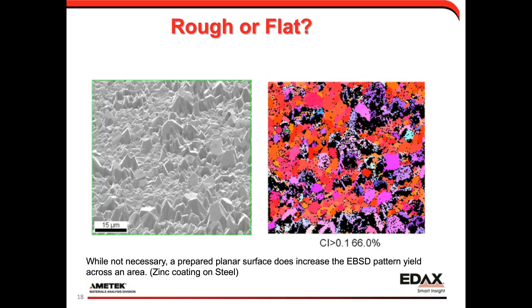I mentioned the surface: generally when we think about preparing a sample, we're going to flatten it out, but it's not really a requirement for EBSD. It just increases the yield of patterns that give us EBSD patterns. This is just an example from a zinc coating on steel, and you can see on the left in the SEM image some faceted crystals. We look at the EBSD orientation map on the right, and you can see from that as-deposited surface, we get usable EBSD patterns from about two-thirds of the points collected.